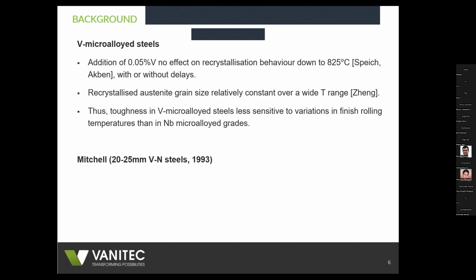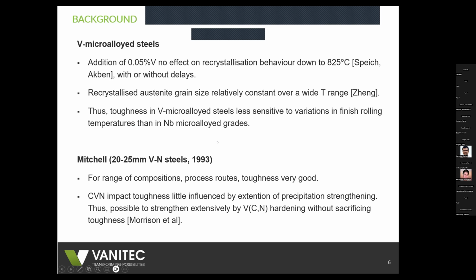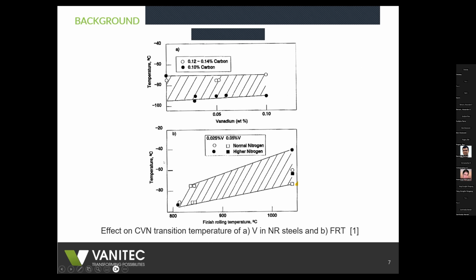Mitchell did some work in the 20 to 25 millimeter range in the 90s, and he found that for a range of compositions, processing was toughness to be very good. He found that the Charpy V-notch impact energy or toughness is little influenced by the extent of precipitation strengthening. Thus, it is possible to strengthen extensively by vanadium carbonitride hardening without sacrificing toughness. And this was done by Morrison, and I think, Dave, you were involved with this as well.